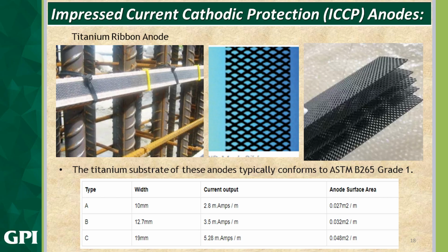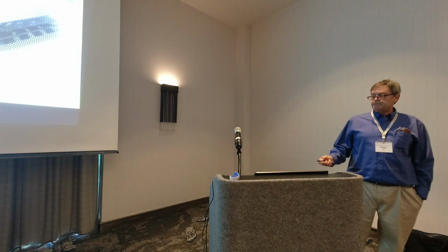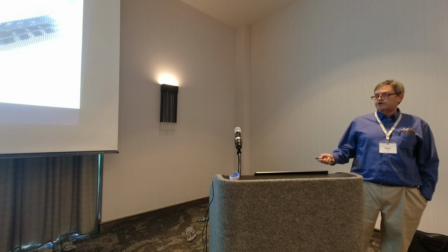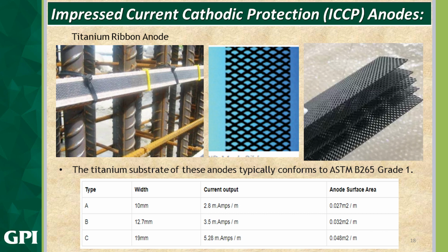Some more on the titanium ribbon anodes. Here's a picture of one in place. Notice the plastic wire ties. The titanium substrate of these anodes conforms to ASTM B265 grade 1. And this is just one of the manufacturers, an excerpt from their product data sheet. It's 10 millimeters wide. I don't know if you can read this back there. It's a little small. 2.8 milliamps per meter squared. I believe that's per meter squared. And then also the anode surface area is given as well.